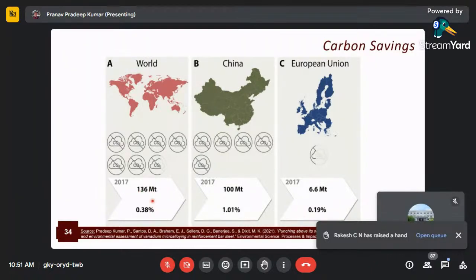So if we just look at the worldwide emissions, we could have saved up to 136 megatons of carbon if we completely used high-strength low alloy steel, microalloyed using vanadium, as compared to using just mild steel across the world. And those numbers are pretty significant in China because China has the highest production of steel across the globe. More than 50% of the steel that's produced around the world is just from China. And that's why the number from China is pretty high, almost up to 100 megatons. Whereas the value from the European Union is pretty significantly low. It's just at 6.6 megatons. So this kind of shows the trade-offs: these values are not consistent or cannot be averaged across the globe. They vary from region to region, and China is a clear outlier as opposed to all the other countries. And that's also owing to the high production of steel in China.